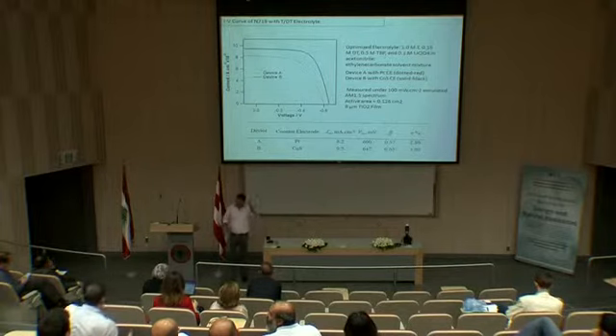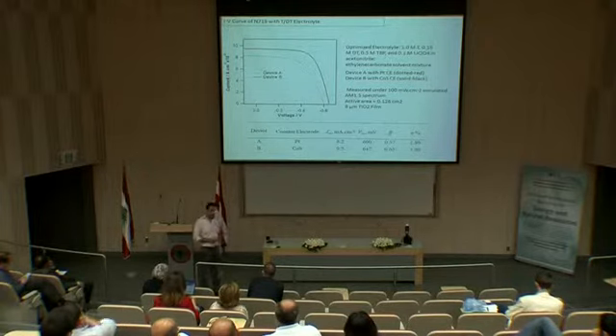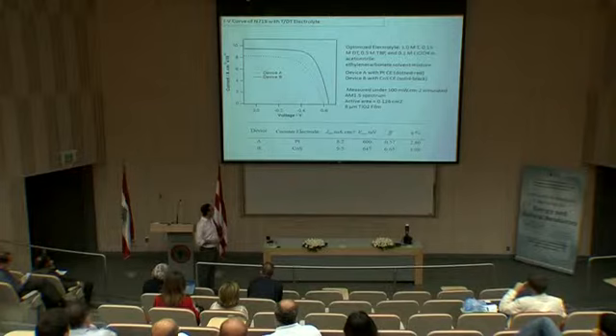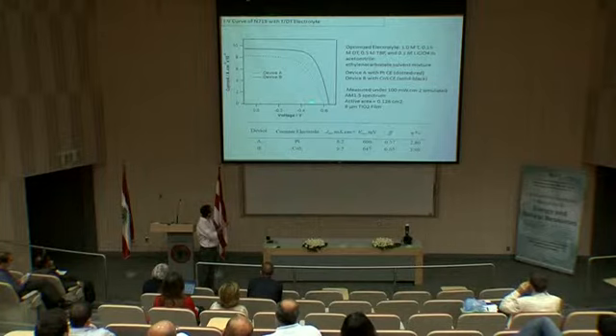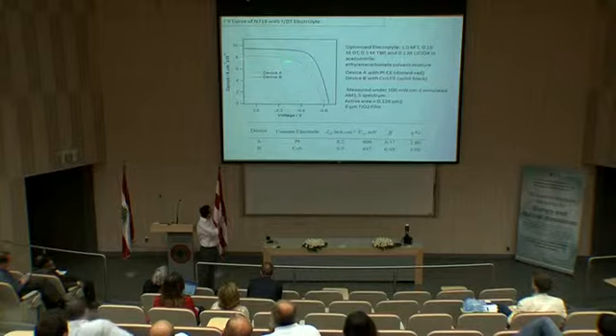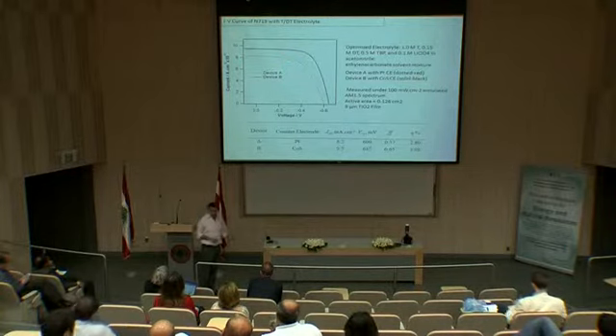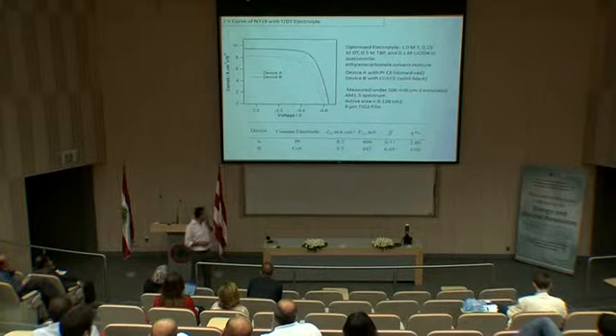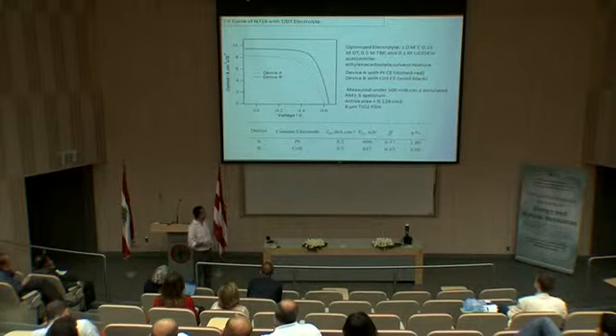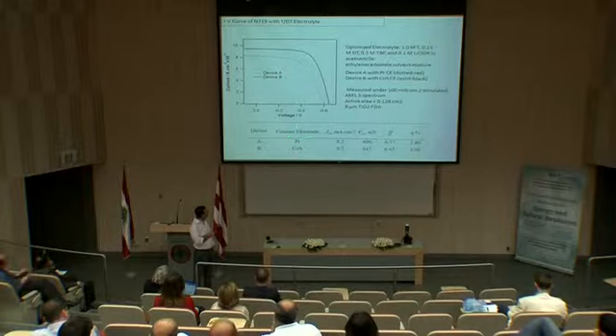Then we make the cells. Usually we use platinum as the counter electrode, a thin film of platinum. Device A is just N719 with this new electrolyte system with platinum. It gave us very low values of current. Voltage does not change because we are not changing much the redox potential of the electrolyte and the titanium. However, platinum was a very bad counter electrode. Even the fill factors are on the low side.